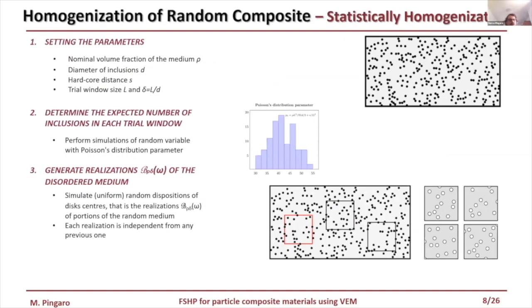As mentioned, in the case of random material, a statistical procedure is necessary. It is possible to summarize the procedure in principle in 6 steps. In the first step, we set the nominal volume fraction of the medium, the diameter of the inclusion, and the hard-core distance between the inclusions. We choose a trial dimension of the window size, and after that, it is possible to define delta, that is the normalized window dimension. It is defined by the ratio between the window dimension and the radius or the diameter of the inclusions. At the second step, we define the expected number of inclusions using a Poisson distribution.